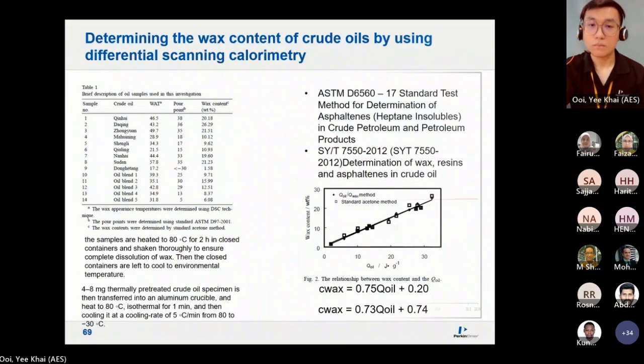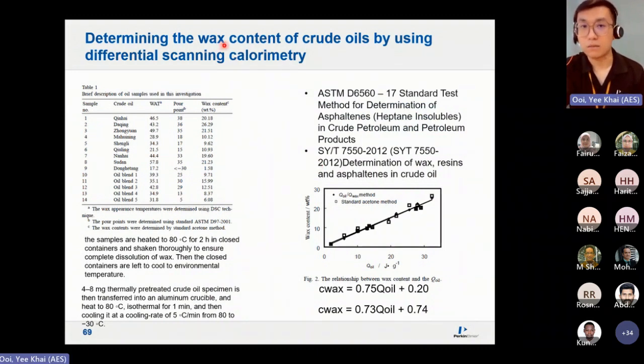In fact, you can also know how much wax is going to precipitate or form from the crude oil by using DSC. We have different standard crude oils with known wax percentages, and then we subject them to a DSC run to determine the peak area of the crystallization peak.